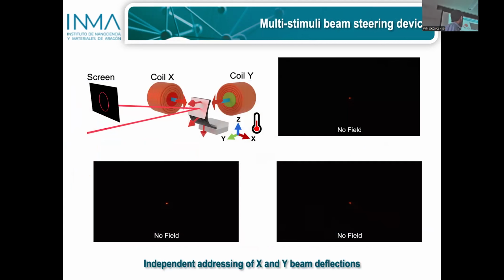And we try to make use of these multimodal capabilities. And here you have an actuator that is a bilayer, a bimorph like the other ones. So by heating it at a certain temperature, the cantilever bends. We have put a small mirror on the cantilever, so a laser reaches it and is reflected onto the screen. So by changing the temperature, we can move the spot up and down on the screen.